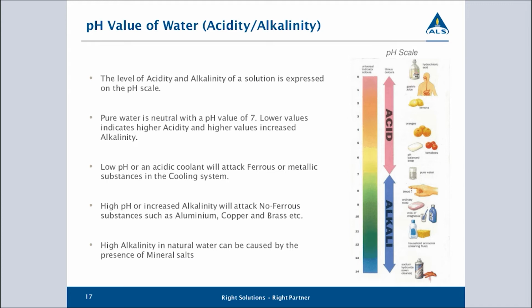The most important thing to be aware of with your pH value is that you want it to run somewhere between 7 to 8, possibly as high as 8.5, but you really don't want it to go much higher than that, and you certainly don't want it to go much lower than that. It should also remain very stable. So if you keep checking the pH over an extended time frame, whatever its original value was, that's what you want it to stay at.